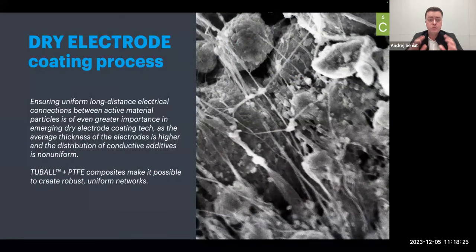In terms of areas of application of single carbon nanotubes, dry electrodes obviously is the direction where we are going. Here we think that our material can become even more essential, because typically the distribution of conductive additives on the surface of dry electrodes is not that good. But if you introduce very long, very flexible structures inside a dry electrode, it's easier to assure very good cohesion between them and assure the uniformity of the conductive network.